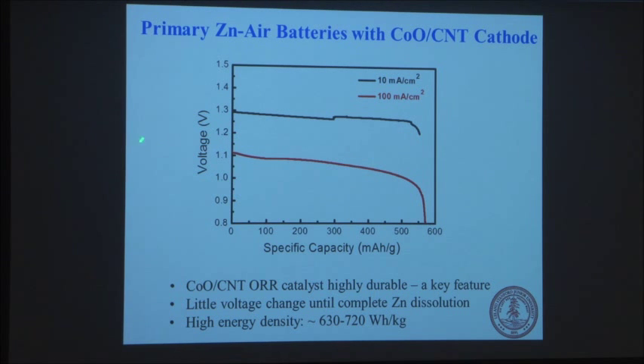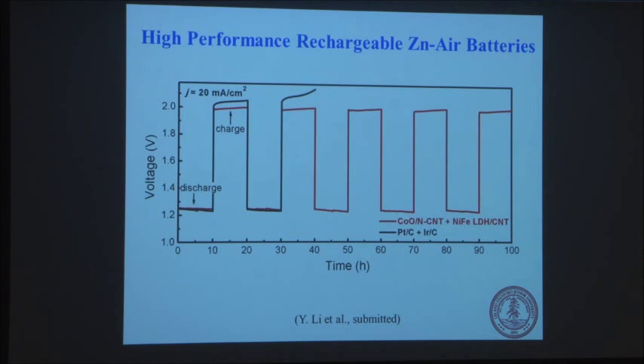So you're basically oxidizing zinc all the way until all the zinc is used up. Okay, so it's got a very good energy density. And then we can also make it rechargeable. So we can oxidize the zinc, okay, for 10 hours. So your battery would run for 10 hours, and then you charge it for 10 hours. What that does is that they put the zinc ions back onto the electrode. So it's zinc dissolving and being plated back and forth. So that's a battery, okay?